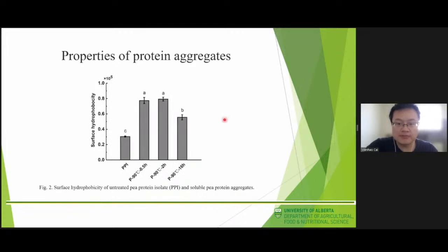The untreated pea protein exhibited the lowest surface hydrophobicity because the hydrophobic groups were buried in the interior of the globular protein structure. The surface hydrophobicity increased almost 3 times when the pea protein was converted to aggregates by heating at neutral pH for half an hour. This was attributed to the protein unfolding during heating to expose the hydrophobic groups.